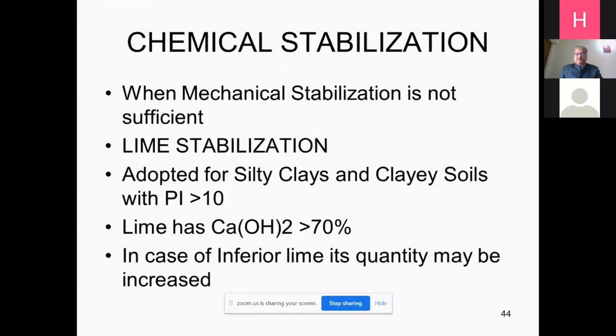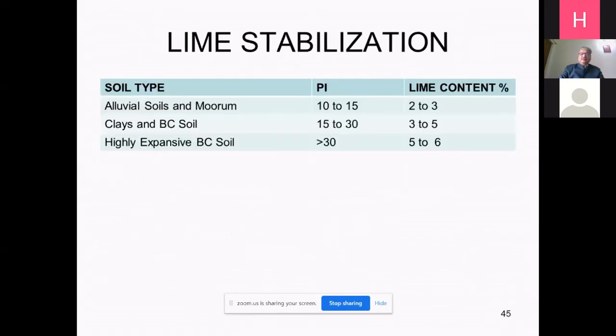It is adopted for silty clays and clay soils when PI is more than 10. But please maintain that the calcium hydroxide content in the lime should be 70% or more. If it is inferior, then you have to increase the quantity of lime. Here are the lump sum requirements of the lime. Alluvial soils and moorams, it is 2 to 3%. For clays and BC soils, it is 3 to 5%. For expansive BC soil, it is 5 to 6%.